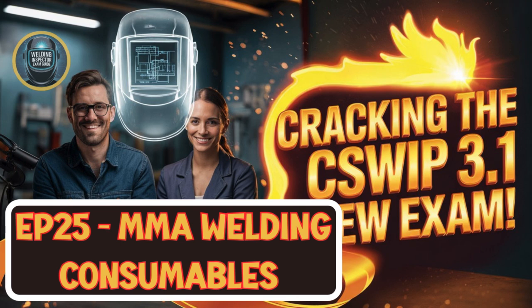Exactly. It creates a really fierce digging arc. This means you get deep penetration and excellent fusion between the weld and the base metal. That lets you weld quite fast without worrying about lack of fusion, which is a potential weak spot. Because of this, cellulosic electrodes are fantastic for welding in all positions, flat, vertical, overhead. They're particularly famous for pipe root runs. There's even a technique called stovepipe welding, often used on pipelines, that relies heavily on these.